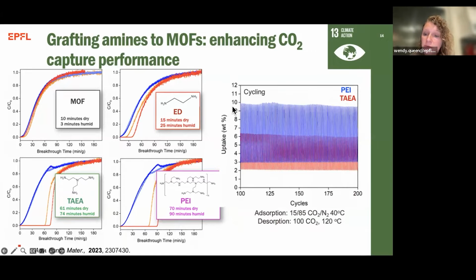And so from there, I told you that we wanted these materials to be cyclable. So we look at the adsorption of CO2 and we look at its release over many cycles. And so what you're seeing is a weight gain due to CO2 adsorption and then a weight loss due to its release. And so here you see our best two performing materials, the PEI and TAEA modified material. We do the adsorption at 40 degrees Celsius, and then we do the desorption at 120 degrees Celsius. So that's how we release the CO2. And here we've cycled the material over 200 times, and we see very good cyclability. We're not seeing significant losses in terms of our material's capacity.